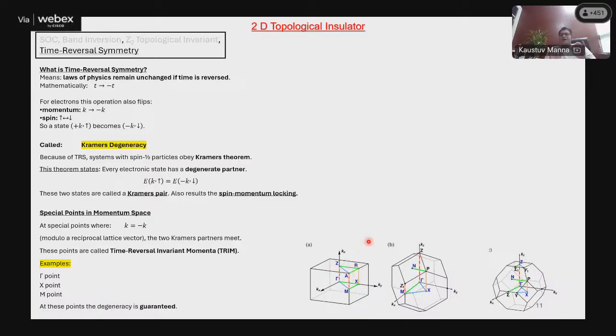So these are the high symmetric points which are time reversal invariant momenta. At this point, the k equal to minus k condition is automatically satisfied. So that means at this high symmetric point, if you have a band crossing, that band crossing is protected by the time reversal symmetry of the compound. So here is the importance of the time reversal symmetry.